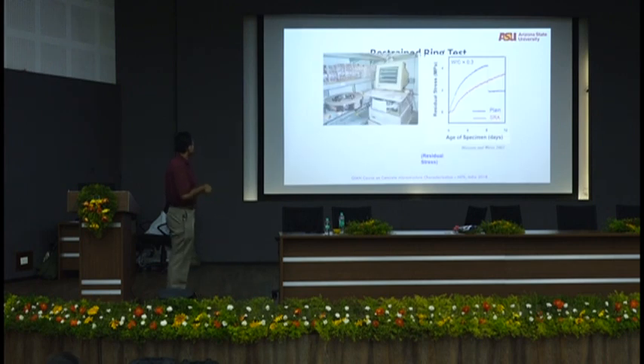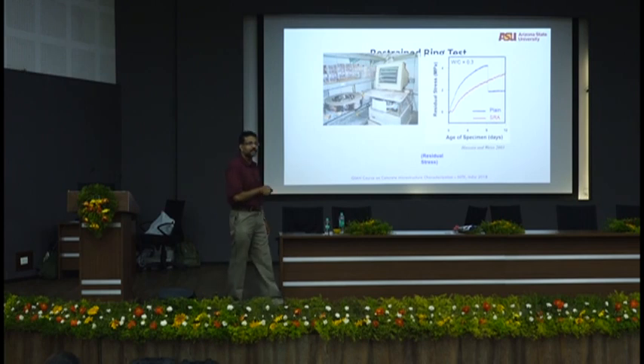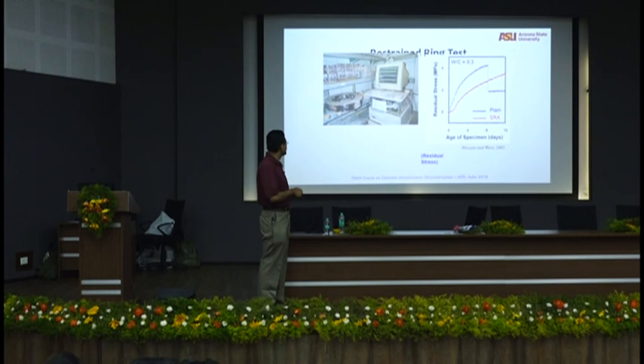Okay, so here is the restrained ring test that I talked about. You have a steel inside ring, steel outside ring. You cast the concrete in between. You have strain gauges all over, and you measure the residual stress as a function of time. Residual stress goes up. Suddenly, when you see the stress coming down, that's an indication of cracking. That's the time of cracking, that's the stress of cracking. We can say 4 megapascal was the tensile stress of that concrete, therefore it cracked at 4 megapascal. In this concrete, I threw in some shrinkage reducing admixtures. It's going on forever. It's not cracking.